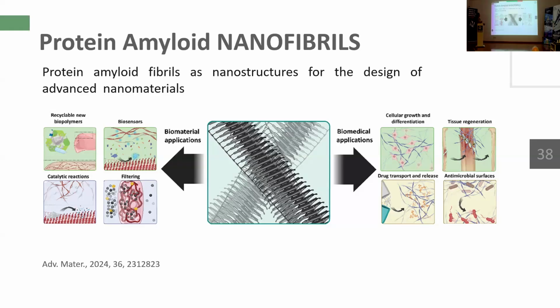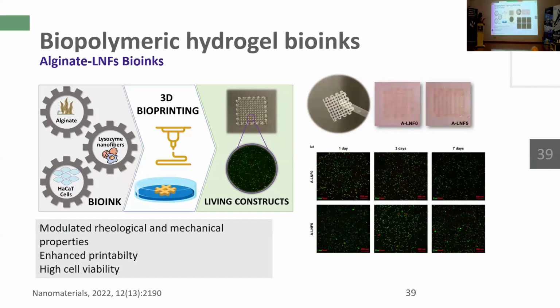In the 3D bioprinting field, we were one of the groups that pioneered the use of these fibrils in 3D bioprinting. This was a very simple and preliminary study where we just confirmed that we can use them. And apart from improving and modulating the rheological and mechanical properties, we also improved the biological properties. In this case, we saw an improvement in the cell viability. And after this very conceptual work, we have been using these fibers not only in bioinks, but also in other materials.